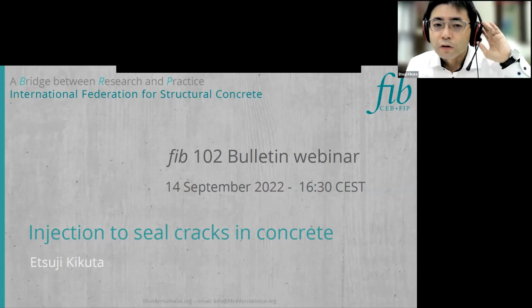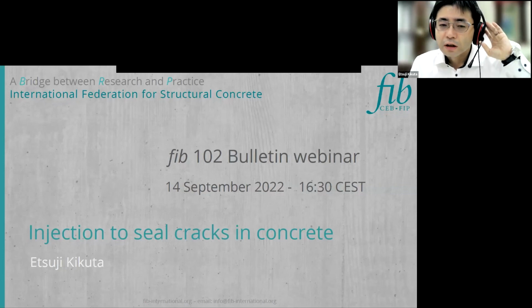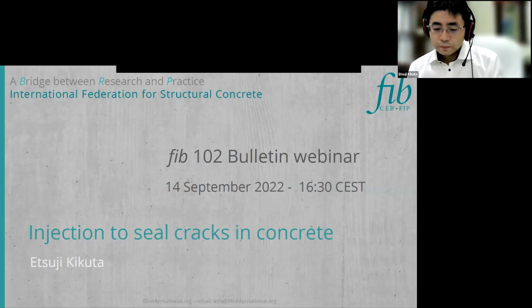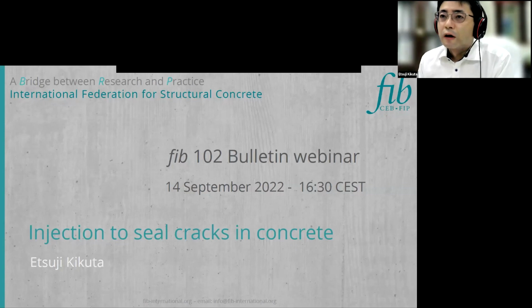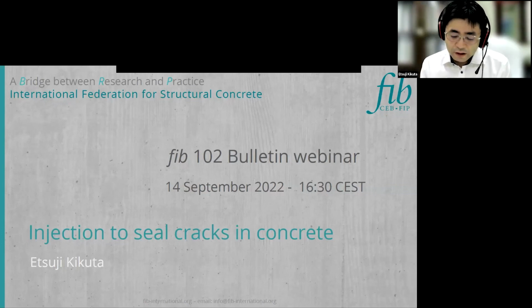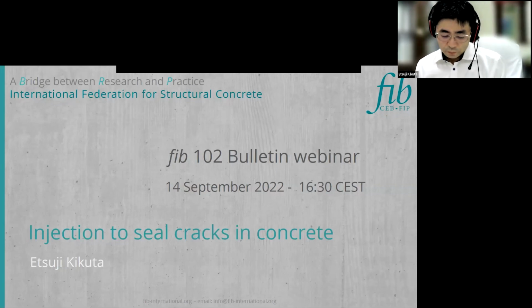Yes, how to decide which method to use: low pressure or high pressure. In this case, since the cracks were linear, it was judged that injection was possible even at low pressure. The low pressure method is easy in execution management, so in this case it was decided to use the low pressure type method.